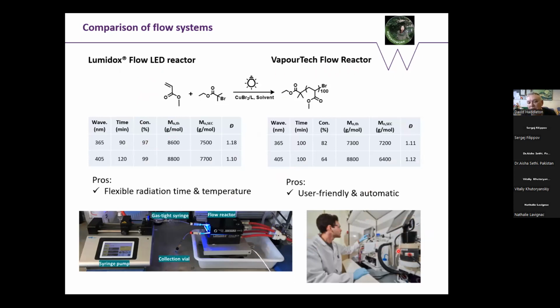So the Vapourtec one is for scaling up. So we can just be pumping it through that for as long as you want to make as much as you want. So just to show you the differences. Again, I'm not going to go through everything. So we're taking about 1.5 hours, 2 hours, depending on the wavelength. So we can change the wavelength, 365, 405. For those of you who don't know, 405 is a particularly interesting wavelength because that's the wavelength that most 3D printers work at. So if you open up a 3D printer, they've normally got 405 nanometer LEDs in there. So 405 we use a lot. So you can then translate this into a 3D printer and use the same wavelength.